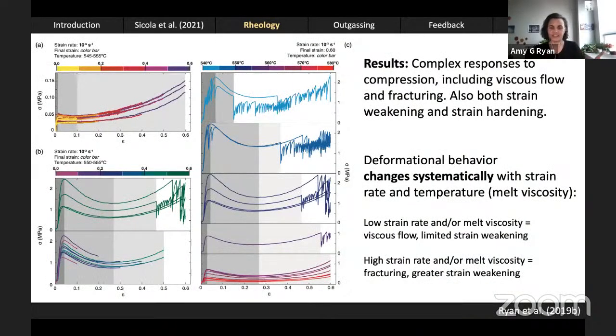These are the mechanical data I collected during my experimental campaign. There's a lot going on here, but that really speaks to the complex response of the material to compression. I observed viscous flow indicated by these smooth curves that you see in a majority of the panels, as well as fracturing indicated by these stress drops in some particular panels. I also observed strain weakening indicated by a negative slope for these mechanical data curves, as well as strain hardening, which is a positive slope that you see throughout.